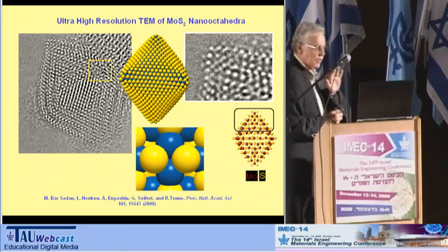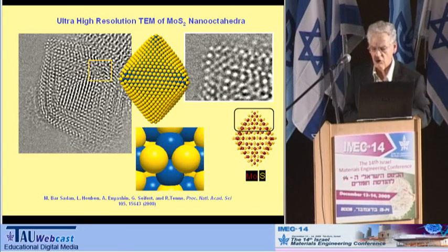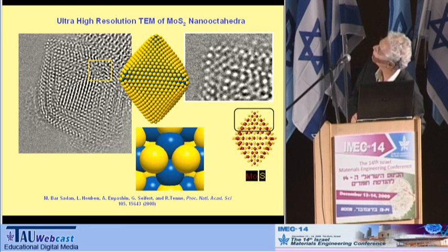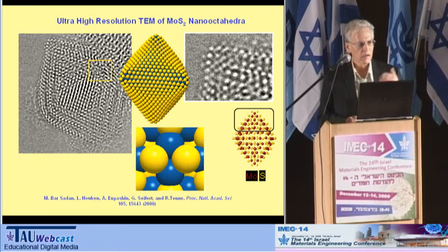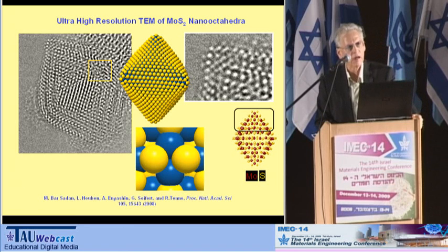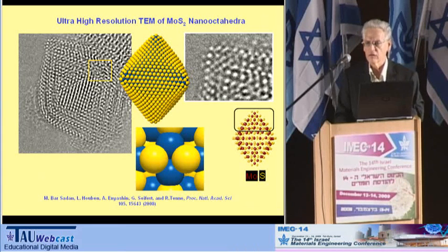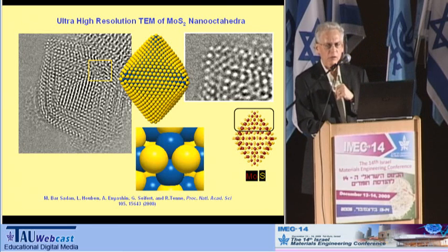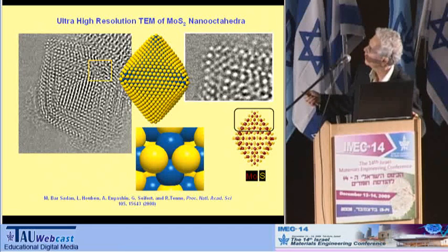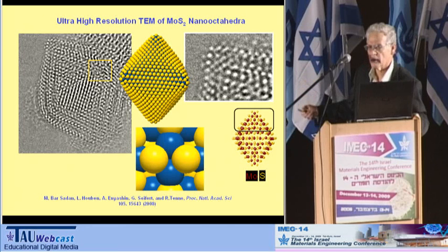Okay, I will just end by showing perhaps this picture, because this picture is very significant. Early on we analyzed the structure of molybdenum disulphide, and we concluded that pentagons are not favorable, and therefore the smallest hollow closed structures of molybdenum disulphide will not be like the C60, which is made of 20 hexagons and 12 pentagons. Instead, they are made of rhombi, corners which are made of 4 atoms, and a large number of molybdenum and sulfur atoms.